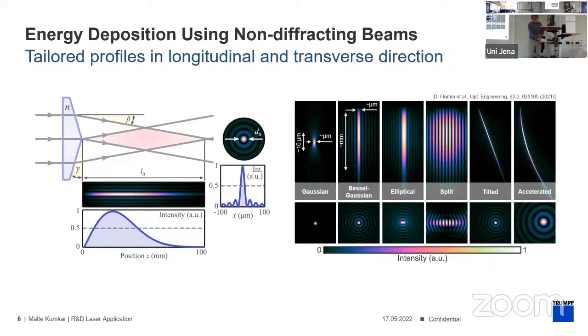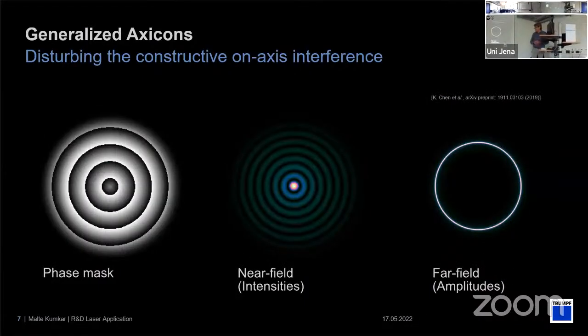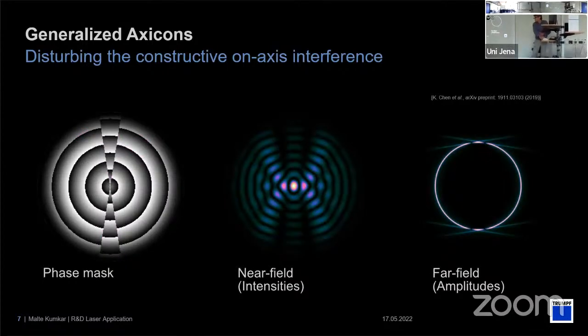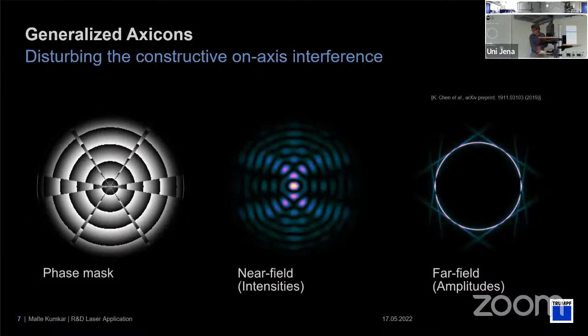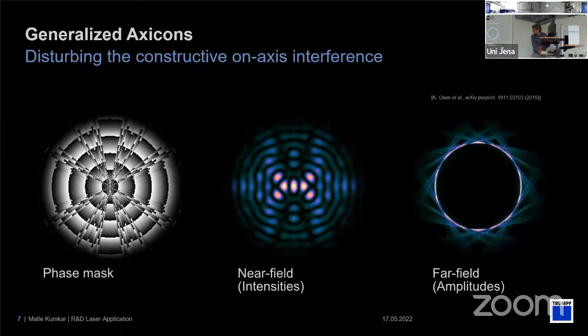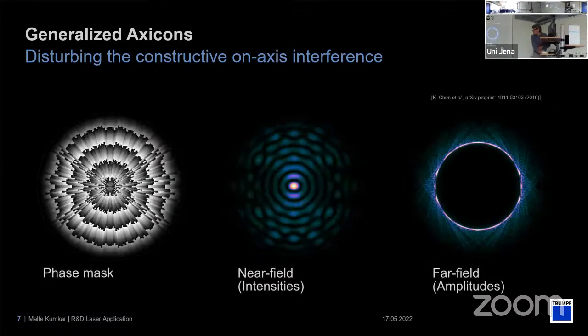And we did a lot of work on this, and I can show a bit of it. So let us start with a phase mask for the Bessel-Gaussian beam. So it's a conical phase distribution, and we have the phase mask on the left, the near field we use for inscribing, and this is the far field, how it looks like. And then we can cut out some segments, modify them, and see what happens. And you can see then, in case, for example, you shift the phase, have the same gradients, but shift the phase in these segments, you get elliptical profiles, preferential direction, or you can make it even more complex. And there are lots of options you can carry out, and some of them are helpful, others not.